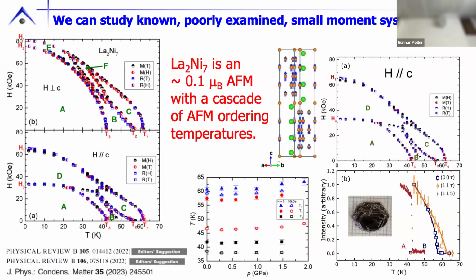Well, then what we can try to do is look at poorly examined antiferromagnets. La2Ni7 has been known for decades, and it was suspected to have very small antiferromagnetic ordering, but the number of transitions and the position of the transitions were unknown, and it was only studied in polycrystalline form.